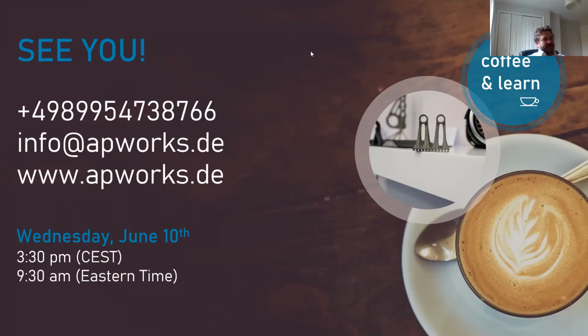So obviously at the start with Scalmalloy, we tried just first to test, run it on aluminum silicon 10 parameters. It didn't work that well, and we did have to tweak the parameters quite a bit. But this might be more things like surface tension of the melt pool and so on that forced us in this direction. But the end result in terms of build-up rate is very, very similar.